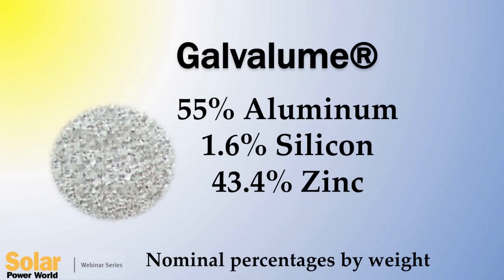If it is pre-painted, factory painted, and of the same approximate vintage, odds are a little bit less, but they're still very good that the substrate is Galvalume. You don't paint instead of a metallic coating, by the way. So every painted roof you see also has a metallic coating beneath the paint. The alloy coating thickness on the base steel sheet is very, very thin, about 0.6 mils or 6/10,000ths of an inch. Just for a sense of scale, a human hair is about 40/10,000ths of an inch. And here we're talking about 6/10,000ths. So to use a technical term, it's mighty skinny.